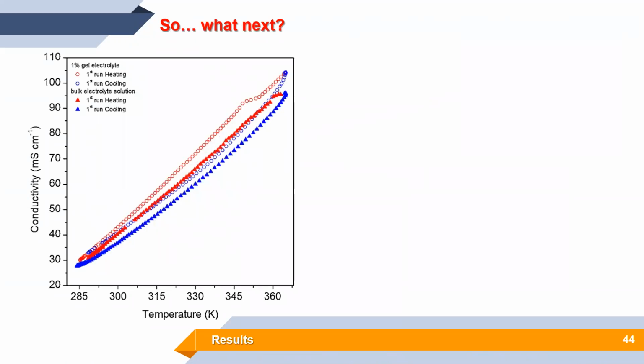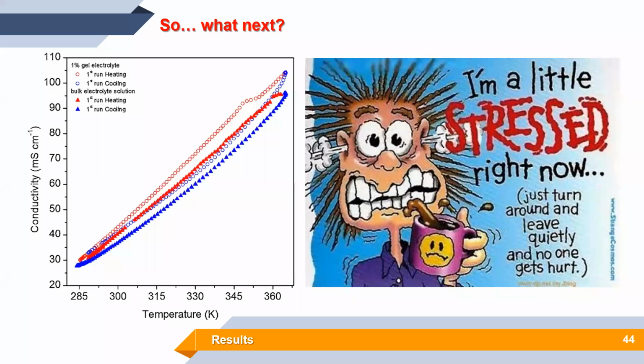Okay, so we now understand why and how the surface diffusion changed in our system, but we still do not know how to explain the enhanced conductivity effect. And at that point, we were a bit stressed because we were really hoping that field cycling would give us the answer. Well, it only shows that in science, in research, you cannot expect that if a solution works for one system, it will also work for another. In that case, the enhanced diffusion at the surface observed for ionic liquid and polymer gel is not working in the case of ionogels.